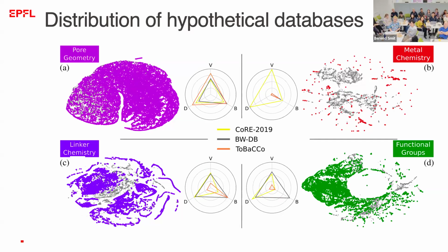And the reason is very simple. We don't have a theory of how to predict a new metal structure. So what you typically do is you harvest the metal nodes from the experiments, and then you add linkers to it in those databases. So in order to make it more diverse, we basically harvested more of those metals and generated a library with a more diverse metal base. So for us, it was much more important to look at a diverse set of structures rather than at a large number of structures. It's important to keep that in mind.